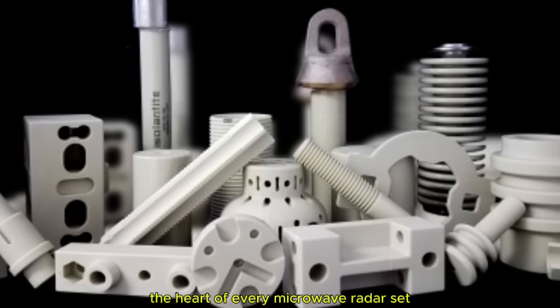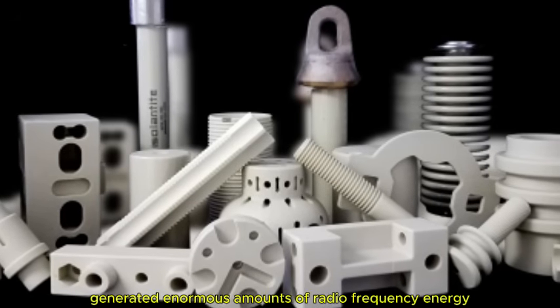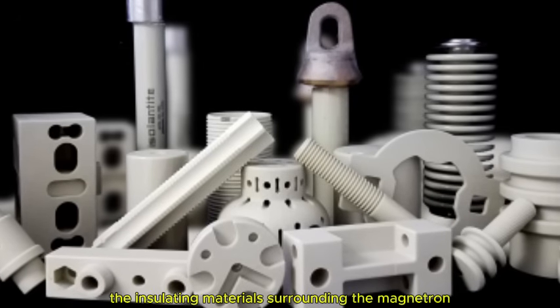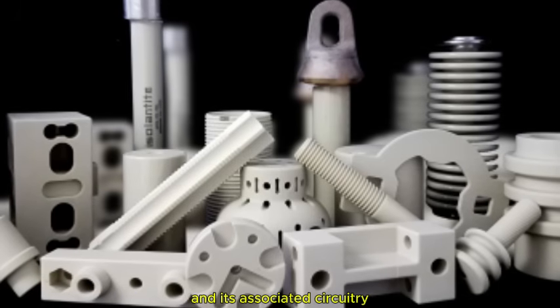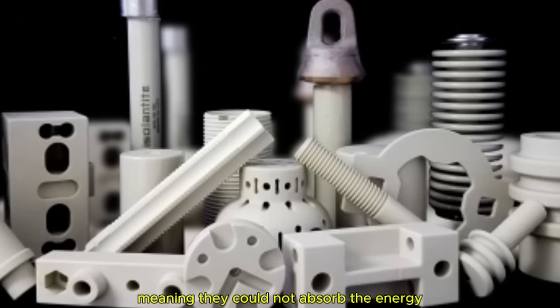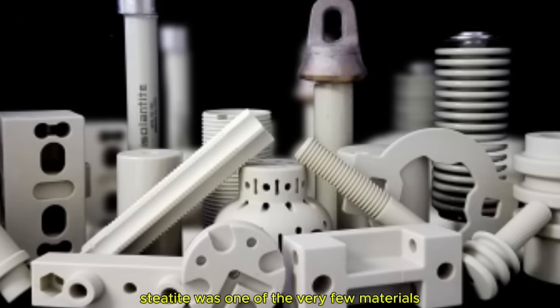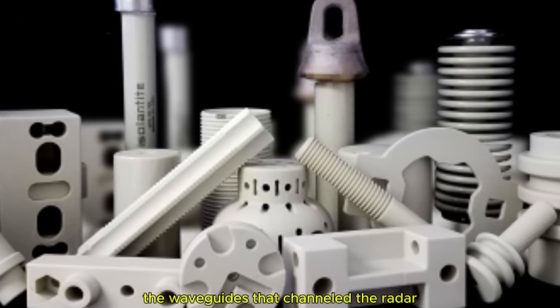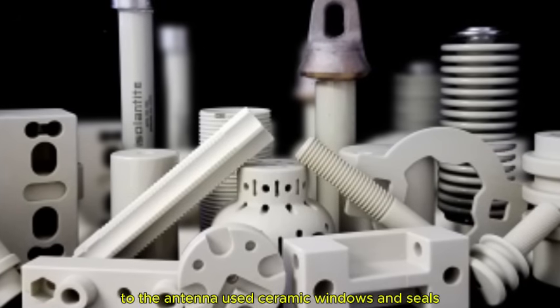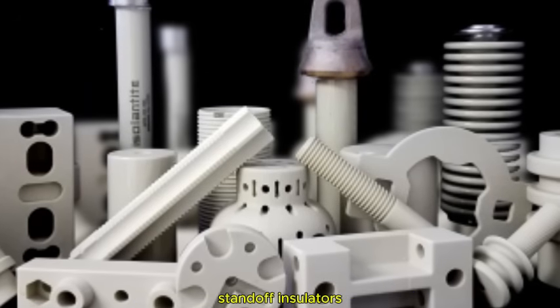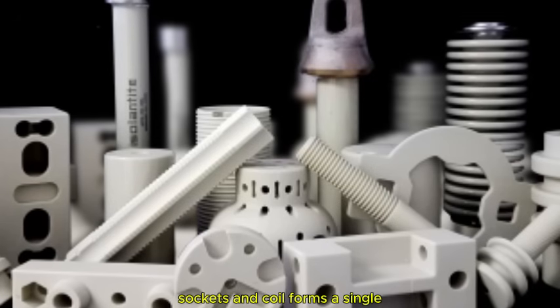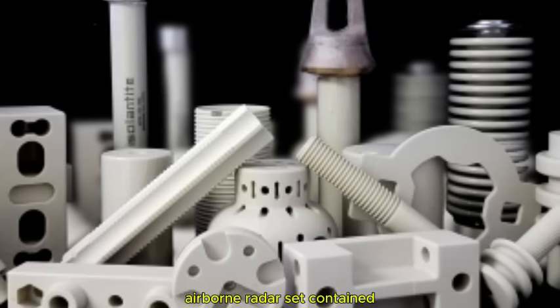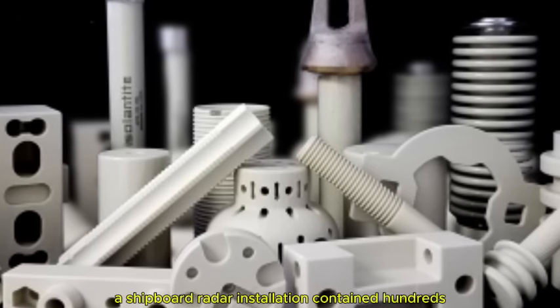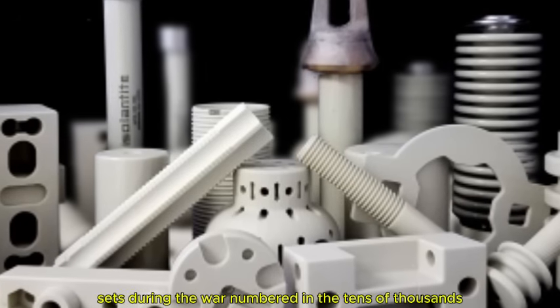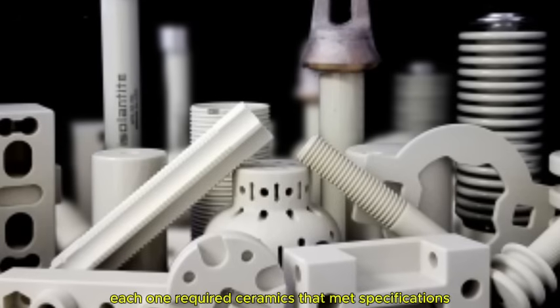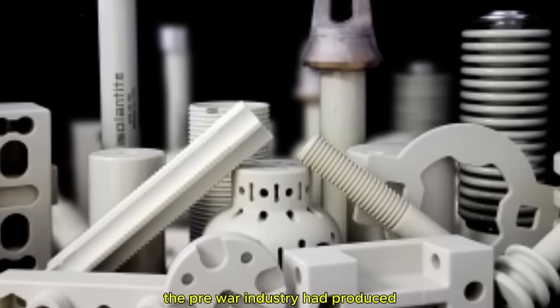The magnetron tube, the heart of every microwave radar set, generated enormous amounts of radio frequency energy at extremely high frequencies. The insulating materials surrounding the magnetron and its associated circuitry had to be transparent to those frequencies, meaning they could not absorb the energy. Steatite was one of the very few materials that met this requirement. The waveguides that channeled the radar signal from the magnetron to the antenna used ceramic windows and seals. The antenna feed assemblies used ceramic standoff insulators. The receiver circuits used ceramic tube sockets and coil forms. A single airborne radar set contained dozens of ceramic components. A shipboard radar installation contained hundreds. The production of radar sets during the war numbered in the tens of thousands. Each one required ceramics that met specifications tighter than anything the pre-war industry had produced.